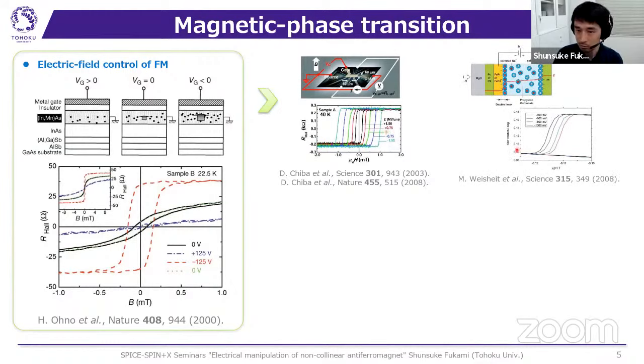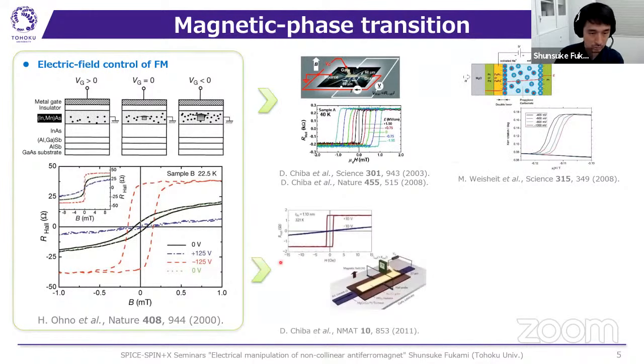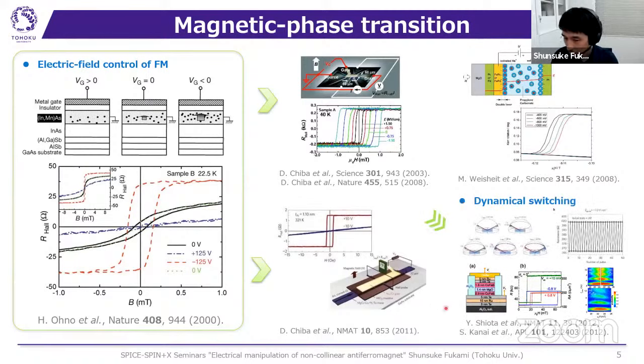And the same phenomenon was observed in metallic systems, and also in metallic systems, the magnetic phase transition was observed. And in 2012, using the electric field induced anisotropy, dynamical switching was demonstrated, in which when you apply the electric field, you can change the magnetic anisotropies and induce the precessions. And so if you turn off the voltage at the specific timing, you can switch your magnetization. So this is the electric field induced magnetization switching.